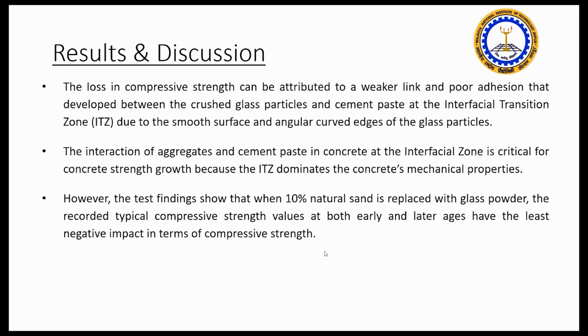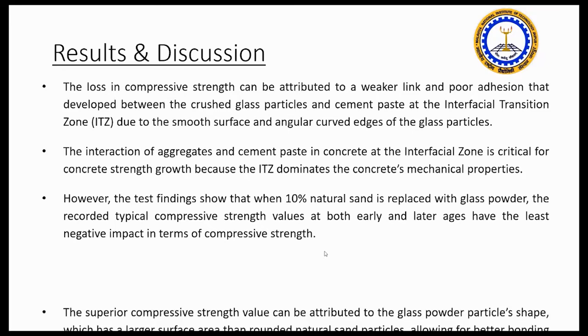However, the test findings show that when 10% of natural sand is replaced with glass powder, the recorded compressive strength values at both early and later stages have the least negative impact in terms of compressive strength. So we can say we were successful in replacing at least 10% of the natural sand with glass powder without any negative impact on compressive strength.